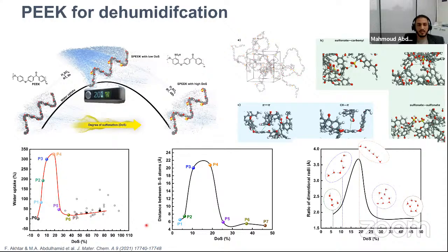And to explain this, we did a simulation. You can see a polymer like this, consisting of SO3H. If you increase the number of SO3H up to 20, all of the SO3H will be able to interact with the water molecules from outside. However, if you go higher, up to 30, 40, or 50, then we will have internal interactions of SO3H with each other, and they will be busy interacting inside rather than interacting with water molecules.